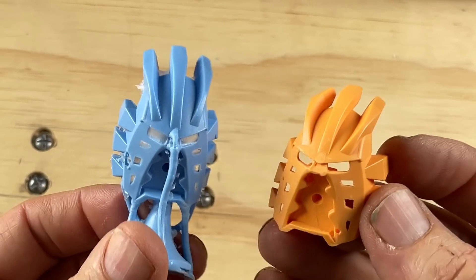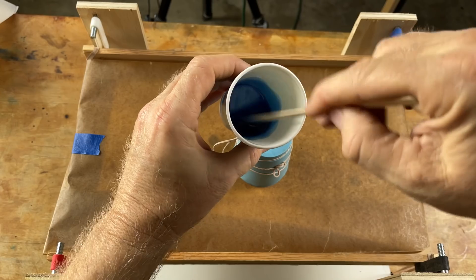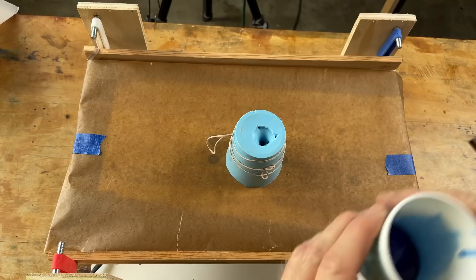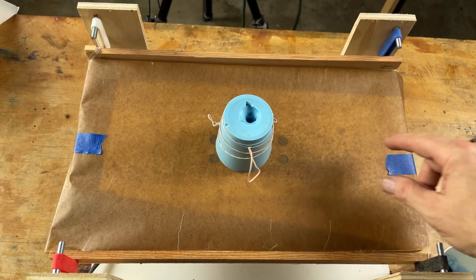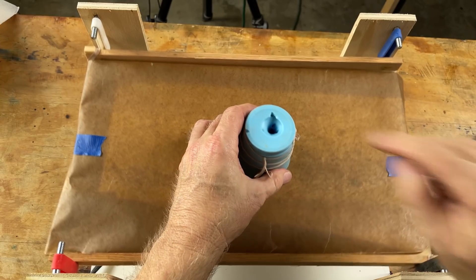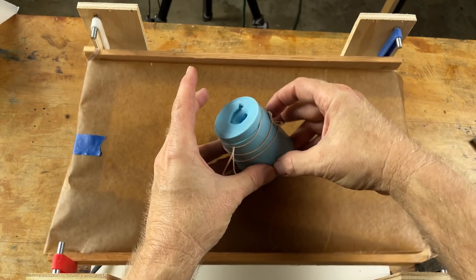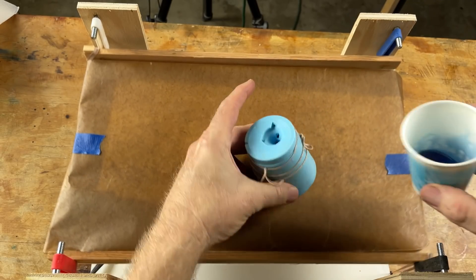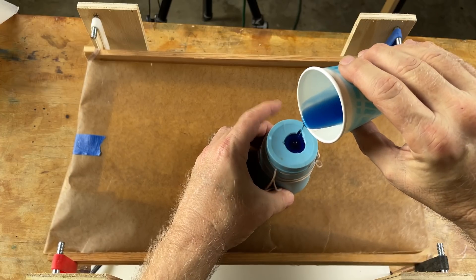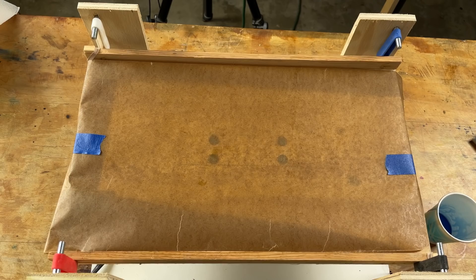So how about a second test? Why don't we do vibration while pouring plus pressure pot and see if we can get a more perfect casting. Got the resin mixed up — going to go quick here. First, let's fire up the old vibrato. I condomized the table because I was getting resin schmutz on it. So we're vibrating, let's pour some in. I notched the mold so I know which way is up. Not only am I going to vibrate, I'm going to rock side to side to see if we can release out of that problem area. Let's head over to the pressure pot and let it do its work.